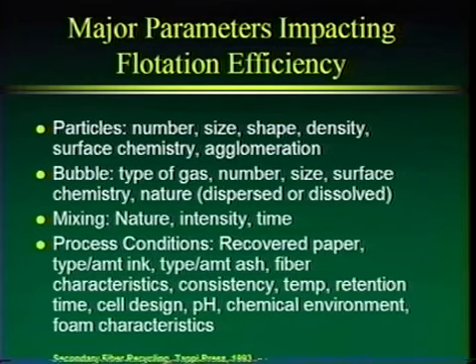Consistency in the flotation cell is important. Remember that if we have too high consistency, then we don't get good mixing, and the fibers can knock the ink off the air bubbles. Temperature can be an issue. Retention time is always an issue. The higher the retention time, the better we get flotation efficiency. Cell design is important. Do we have too much turbulence in our system? Can we introduce a lot of air bubbles but not have them agglomerate? pH can be a factor. Chemical environment, how much surfactant is in there? What are the foam characteristics? Is it strong enough to take the ink and keep it separated from the stock?